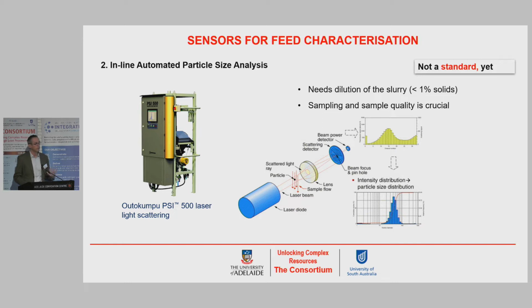But then we may want something more, because we know that flotation is very sensitive to particle size, and therefore very recently there has been a lot of interest in having inline and real-time particle size. And within the PRIF we have something like that as well. So a couple of examples of how this can be done. There is automatical particle size done by laser diffractometry, which is a system which is out there and marketed by Outokumpu. It's basically like having a small Malvern master sizer embedded in an instrument which can put on site. So it's based on laser scattering.